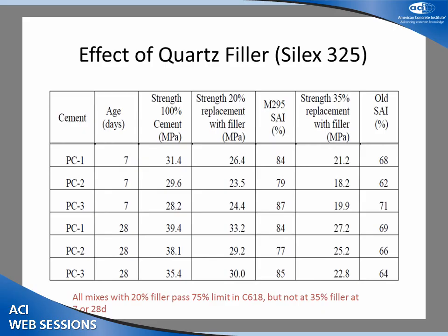So here's three different Portland cements of different alkali content, C3A, 7-day strength, 28-day strength. There's the one with the filler, so that is the strength activity index in ASTM C311, which is the same as C618. So we passed the test at 7 and 28 days with 20% ground quartz, which is what you're asked to test it at now, 20% ash. So it's really not giving us anything.